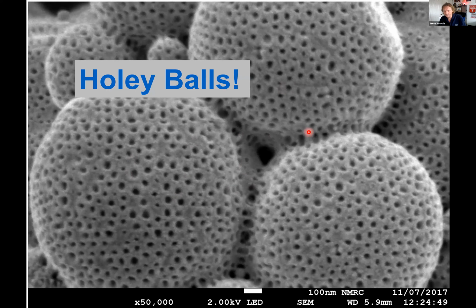And we ended up creating these things, which we called holey balls. You can see that these microparticles have now swollen a little bit and are very porous. The pore sizes here actually correspond very well to the domain sizes of the vinyl pyridine that was inside the structure.